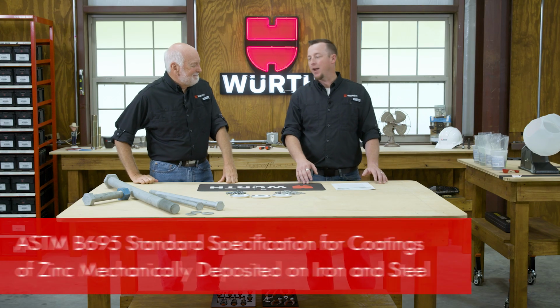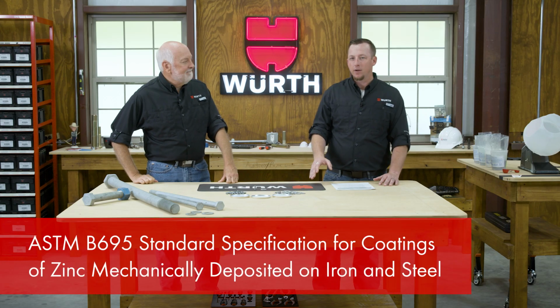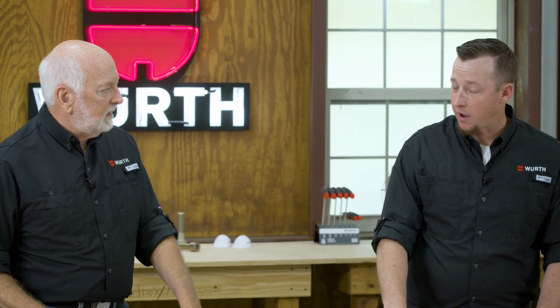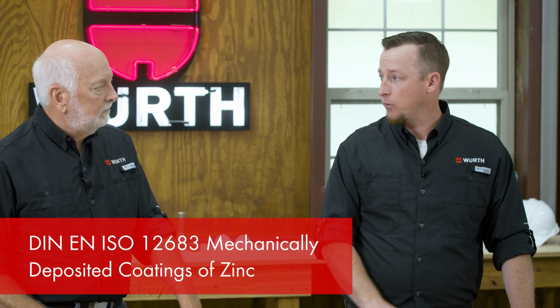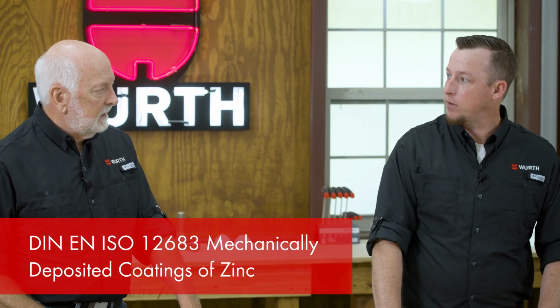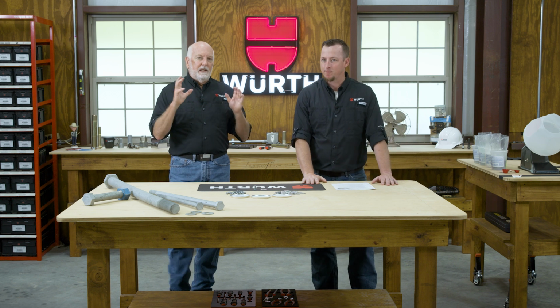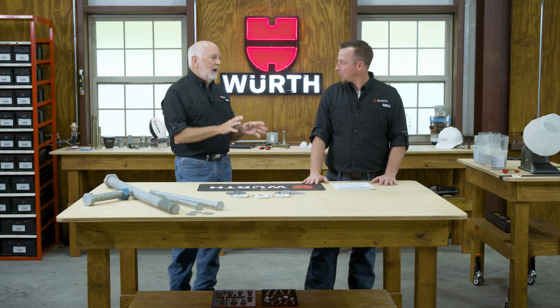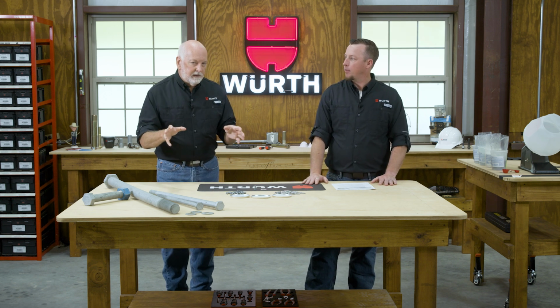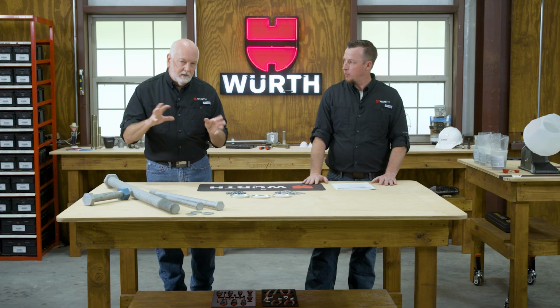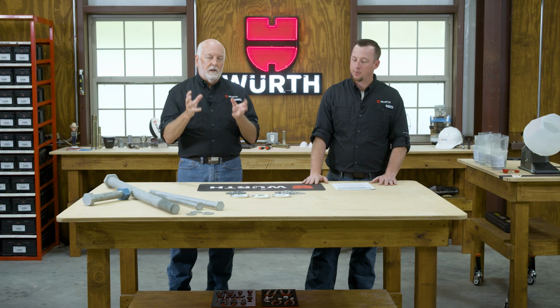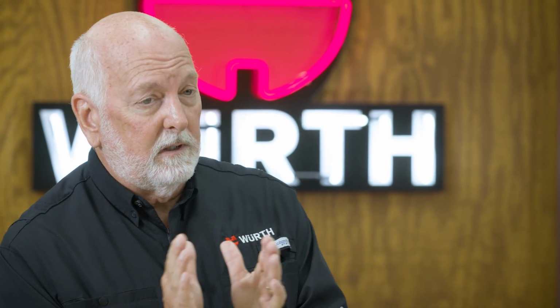So we're talking about ASTM B695, and also on the metric side, ISO 12683. Those are the two standards that cover this. That is correct. So these specifications do talk about accelerated test and salt spray hours, salt fog, salt spray hours. So we're going to talk about that. Down in the very thin, you can put very, very thin coatings on there that are in the 5 micron, 0.2 of a thousandth area.